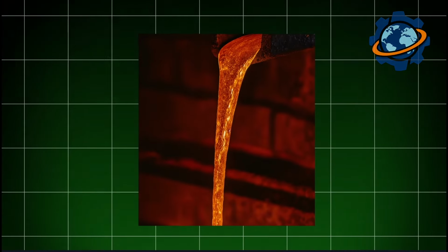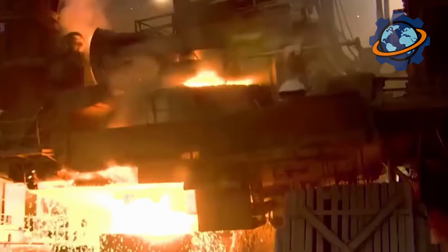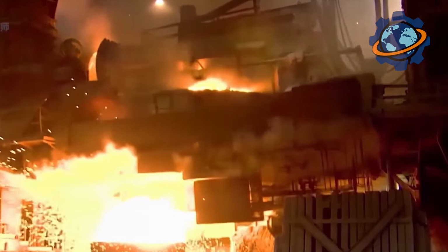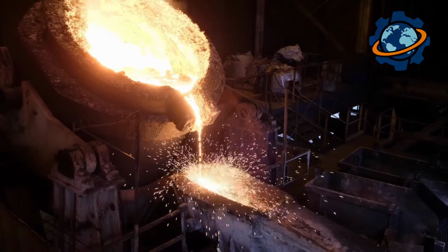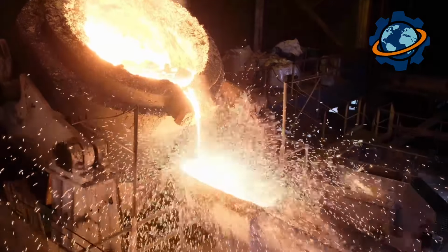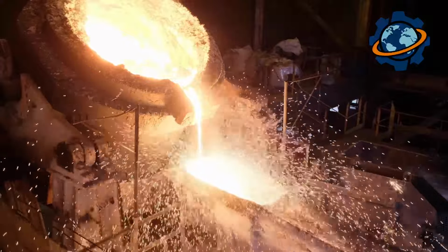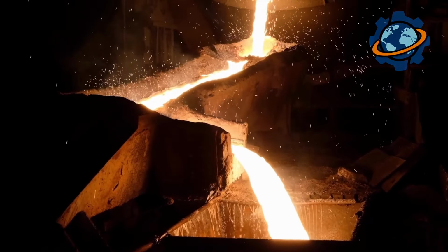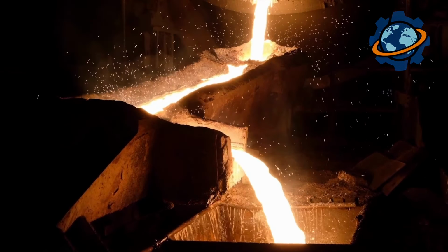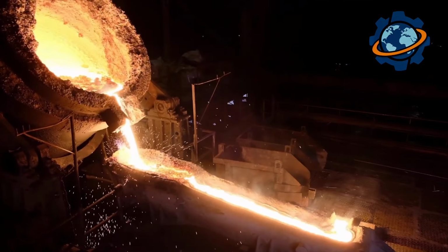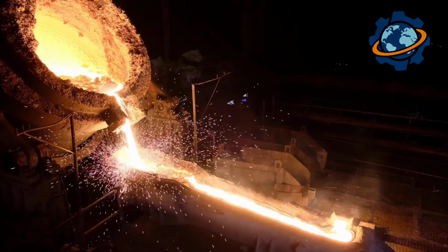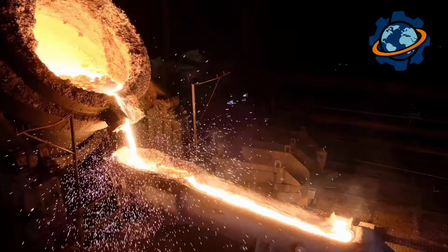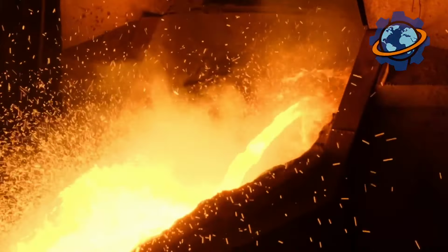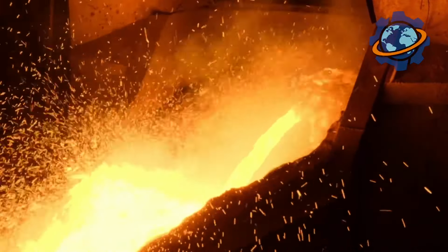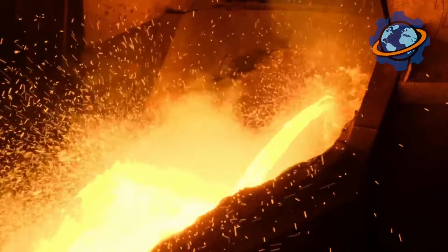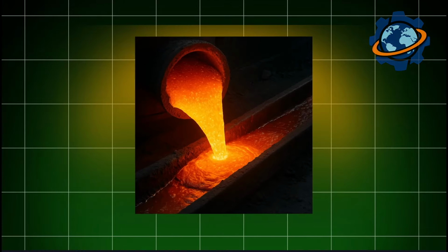Then steel gets cast. There are 2 methods. First, continuous casting. Molten metal pours into a crystallizer, a water-cooled copper mold. Below, a solidifying blank emerges, a slab 8 inches thick, 6.5 feet wide. It glows red, with surface temperature around 1,800 degrees Fahrenheit. Gas cutters slice the slab into 33-foot lengths, each weighing 25 tons.